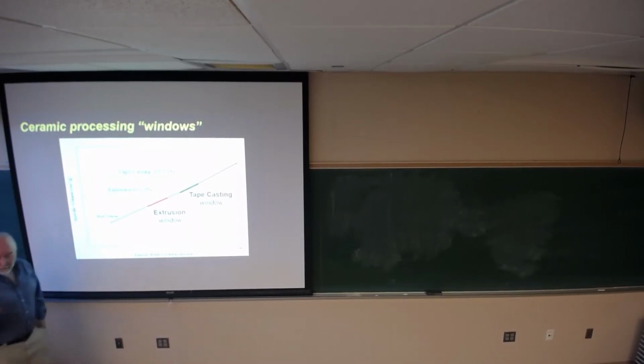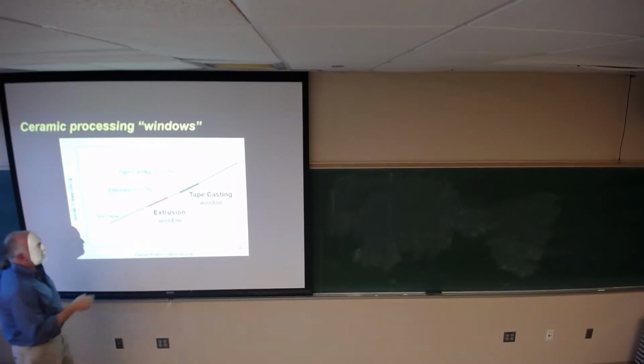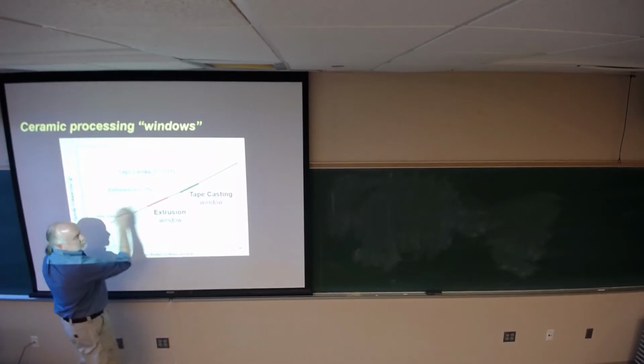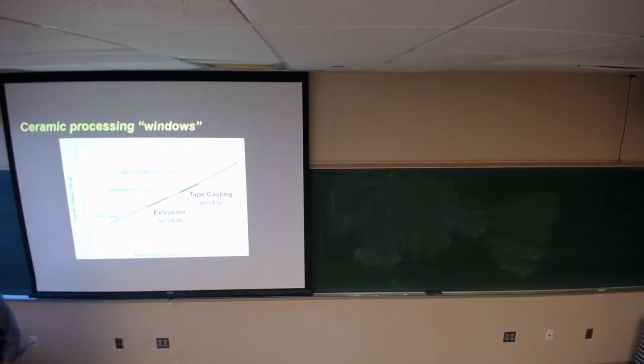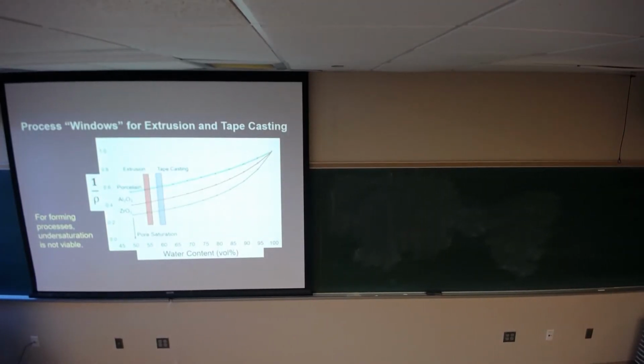Now I would go one step further if you're familiar with robocasting, 3D printing technology, right? Joe Cesarano is giving a seminar tomorrow on robocasting, as it turns out. If I was Joe, I would push this to be slightly oversaturated or have excess water in it to improve the adhesion of the layer that he printed a minute ago to the layer that he's printing now. By going a little bit of excess, not too much. You go too much, the system becomes sloppy. But you want to be on the upper side of that window potentially to improve the bonding between the layers, because that's an issue, right? Tape casting, same sort of thing. So that window doesn't change based on the material that I'm working with.